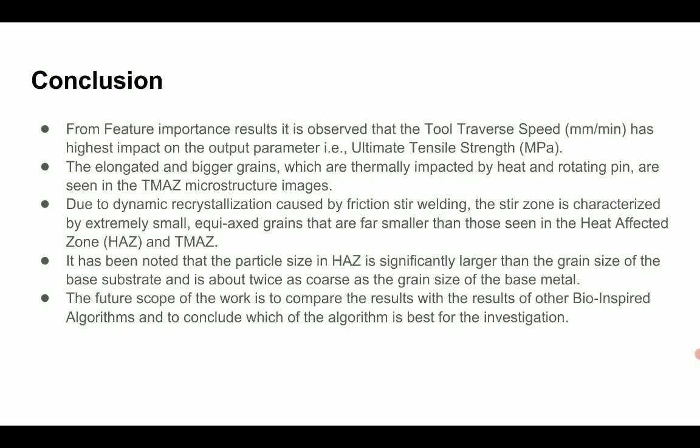It is observed that tool traverse speed has the highest impact on the output parameter. From the microstructure analysis, we see that the elongated and bigger grains, which are thermally impacted by heat and rotating pin, are seen in the thermomechanically affected zone (TMAZ) microstructure images.